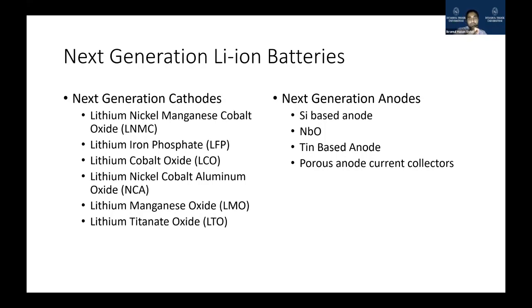But silicon based anodes are also a little bit trending right now, and I am personally working on silicon anode as my PhD thesis. We are doing silicon synthesis through electrochemical deposition, and then we are using it as anode. This time we do not need to use any binder, or any type of toxic material to mix it. So silicon is also a very trending next generation anode that can be replacing the carbon or graphite anode. But it goes through very high expansion.